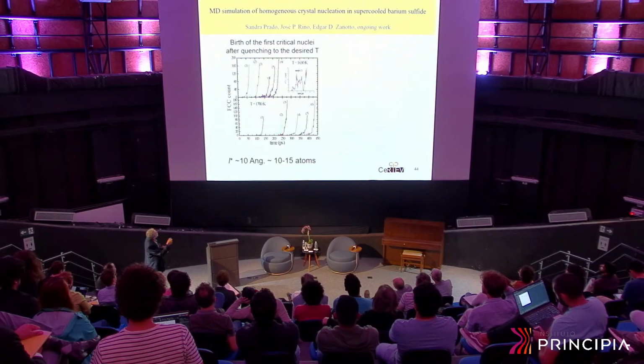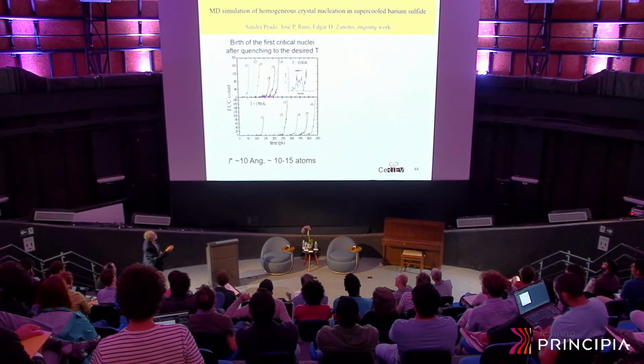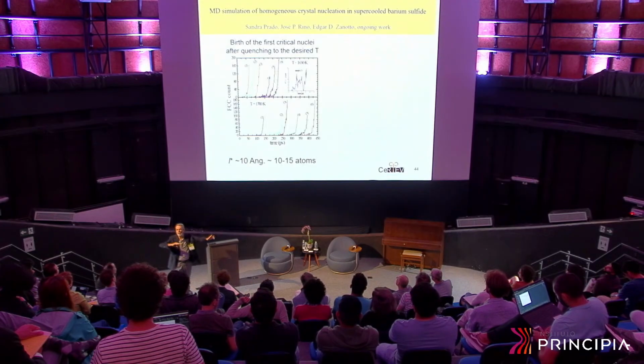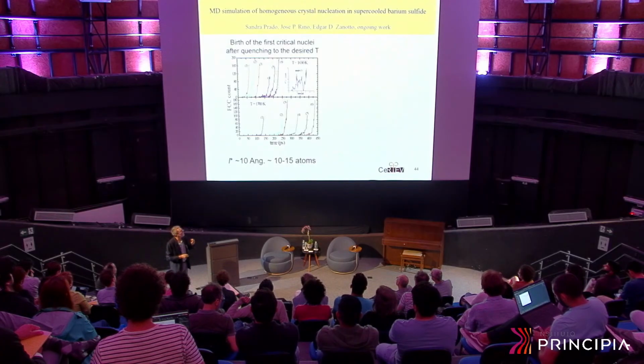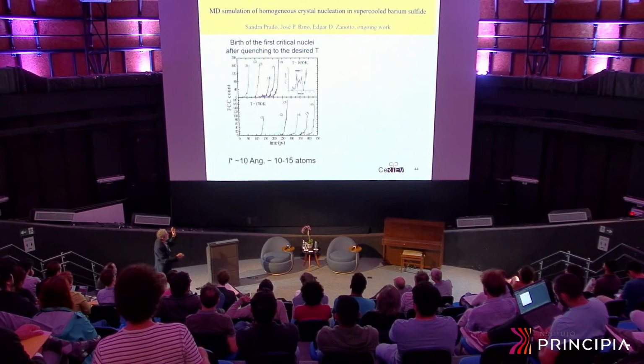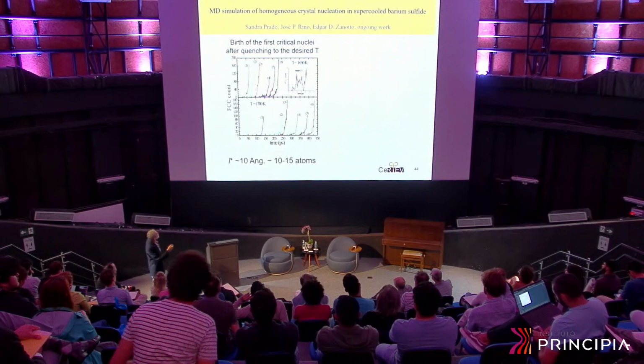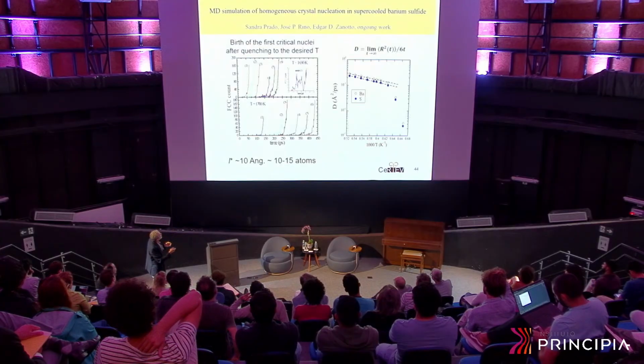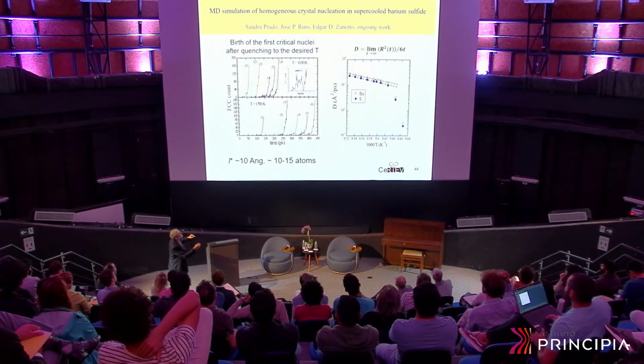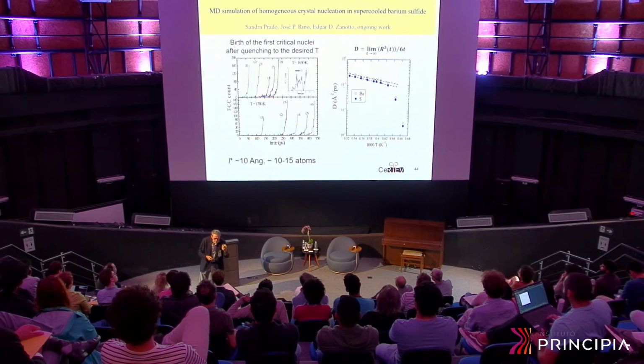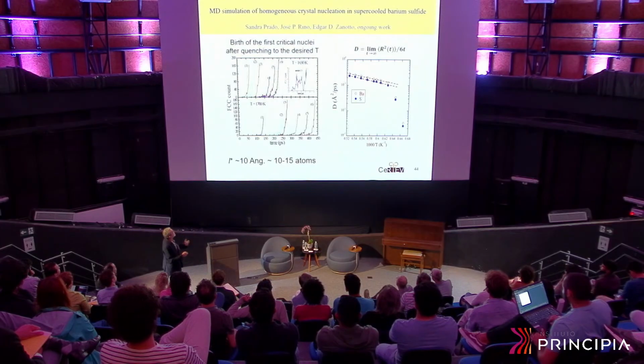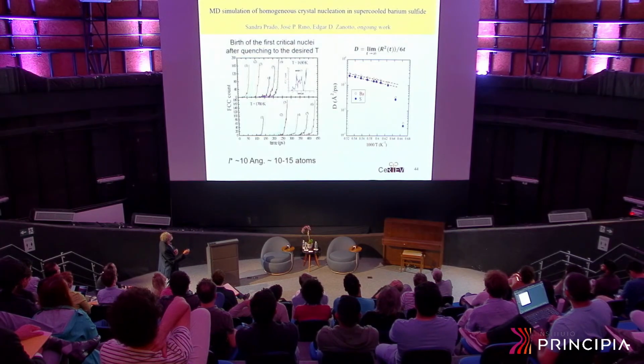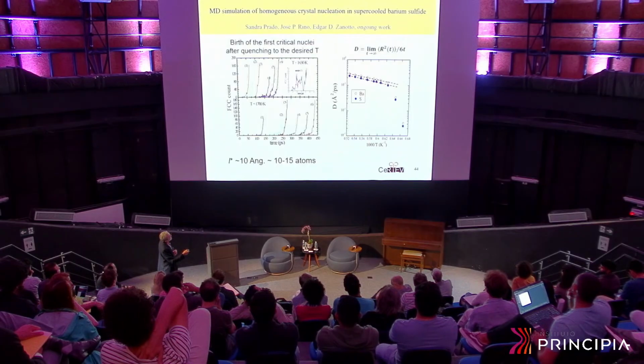You can then compute the time to form the critical nucleus in simple systems for which reliable potentials are available. The potentials have been tested with many other types of properties. There was a very reliable potential for barium sulfide. That's why we picked barium sulfide, just because the potential was good and tested in many other situations. So let's see if we can measure these things. We could measure. And then also the diffusion coefficient. This is good news because the MD simulations can give you the true diffusion coefficient also. So we can get the diffusion coefficient. In this case, barium and sulfur, they are about the same. So we just took the average because they are almost the same.